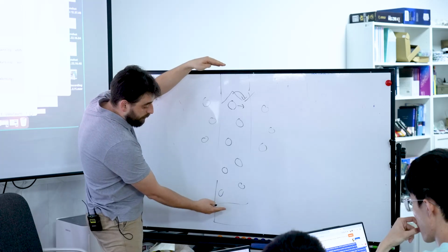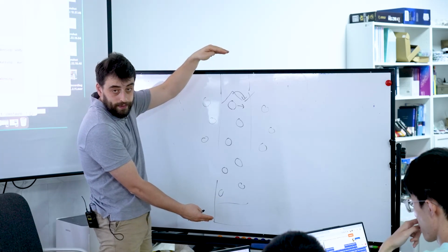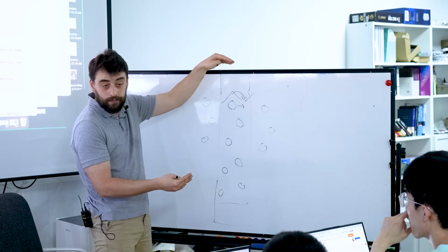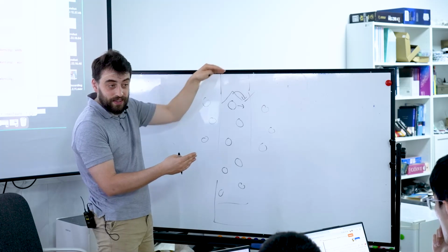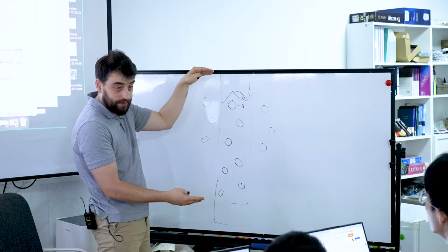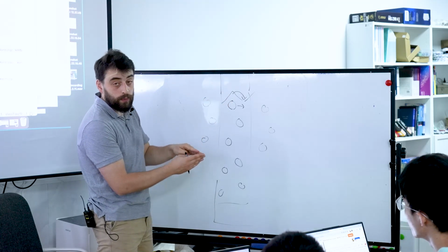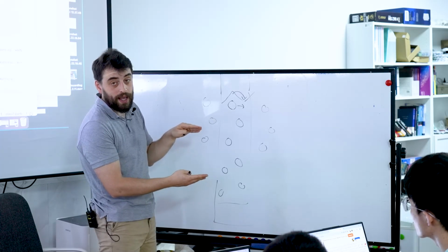If we make this bigger and bigger and bigger, the electrostatic interaction will decrease very quickly. But, as you know, the dipole order term will not decrease so quickly, right? The dipole order will take longer to decay. And so we may still have dipole interactions between the top and the bottom, even when we have a large vacuum gap, okay? If we have a charged surface.